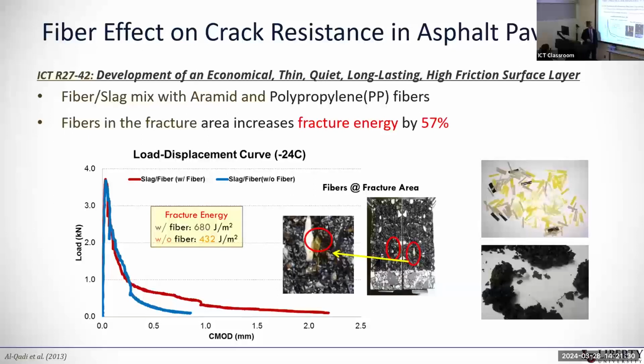So when we used the aramid fibers, it actually improved the fracture energy by 57%. So there's a possibility to improve the fracture energy by using fibers in asphalt materials. And as you can see here, this fiber actually reaches the cracks when there's crack propagation. So we try to use these chopped fibers to bridge the cracks during the crack propagation.